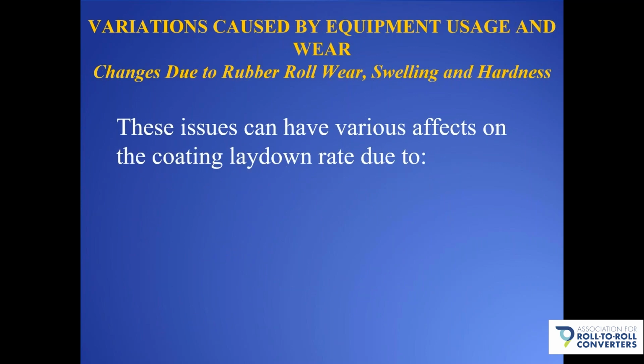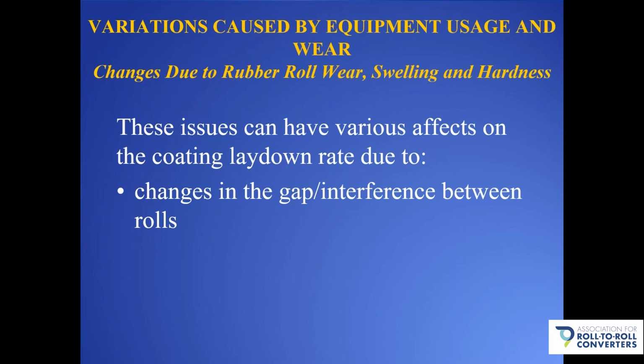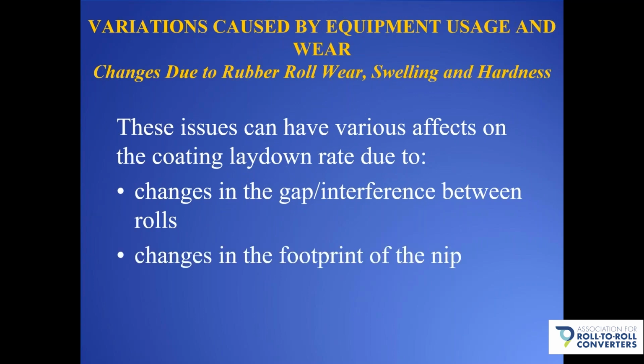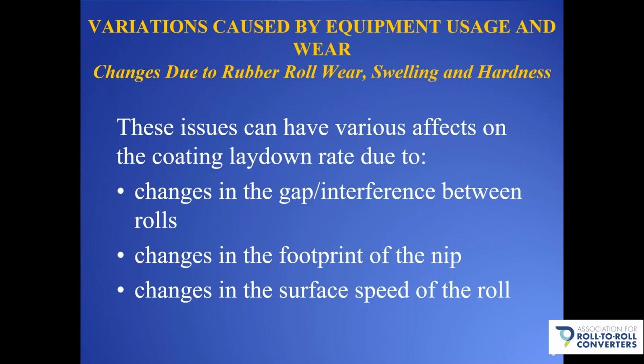Now, these issues can have various effects on the coating laydown rate due to changes in the gap or interference between rolls, which can affect how the coating is transferred from roll to roll or roll to web. Changes in the footprint of the nip, which again can affect transfer from roll to roll, or in the case of gravure, the inability to properly remove the coating from the cells, or changes in the surface speed of the roll, which again can impact the transfer of coating and the proper laydown rate.